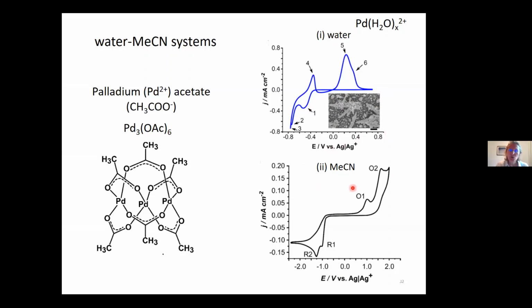However, when you do this in pure acetonitrile, you still see reduction behavior. You still see palladium 2+ going to palladium 0, but your oxidation peaks are way more shifted out. Plus, you don't see any evidence of the palladium metal itself on the electrode surface. So this was interesting to us because it was saying, okay, if we take the palladium acetate in acetonitrile, we cannot do electrodeposition. Some of you may realize immediately why this is. So we thought we knew why this was, but we thought we really need to prove this as well.